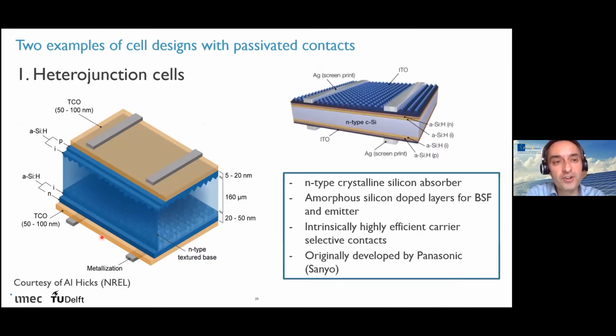The first one is a so-called heterojunction cell. Why is it called that? Because you typically have an N-type crystalline silicon absorber, and you passivate it on both sides with very thin amorphous silicon layers. You also use the amorphous silicon to create a back surface field and an emitter. Because you have the combination of crystalline silicon and amorphous silicon, we call it a heterojunction cell.